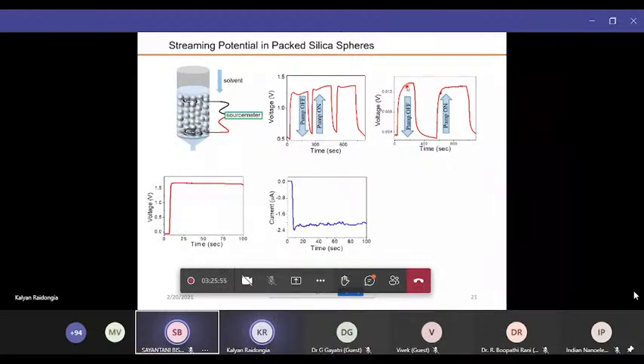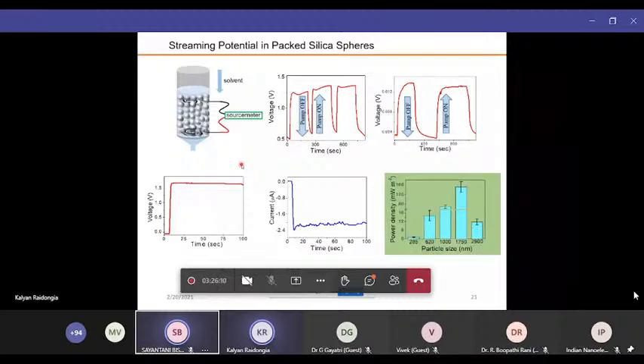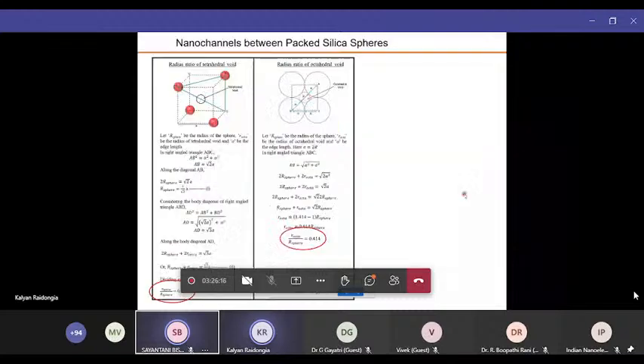So typically, whatever papers were published before that, most of them were dealing with microwatt per meter square range energy. Just by tuning these channels, we can increase the power almost 100 times more. Similarly, we can also have spheres of different dimensions and see what dimension shows the maximum power. I'll not go into much detail on this, but we can directly find out from the calculation what the dimension of your spheres is, which is directly related to the dimension of the holes or the vacancies between the spheres.